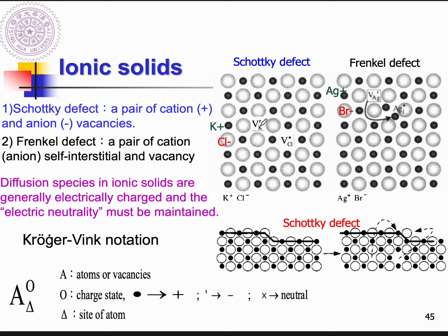It was a potassium ion, but the potassium ion left or was removed. So this vacancy is now at the potassium site and with one negative charge, because the potassium had one positive charge, and then the potassium left, so the vacancy becomes one negative charge. So we get a prime here. So you can practice.